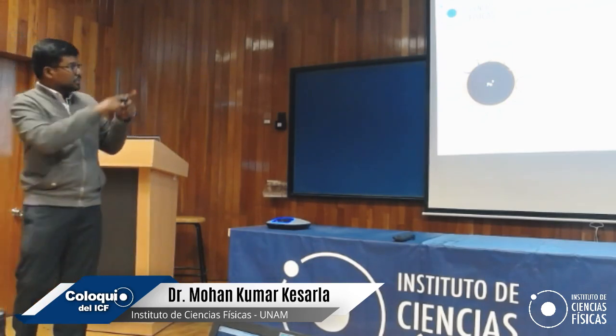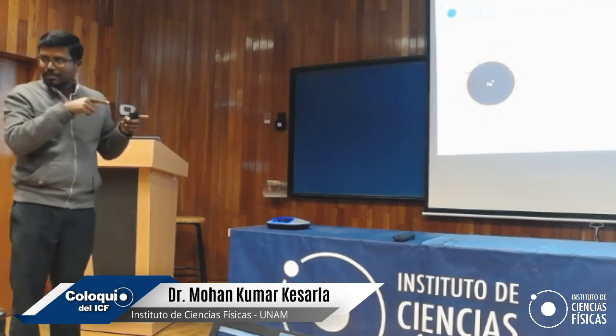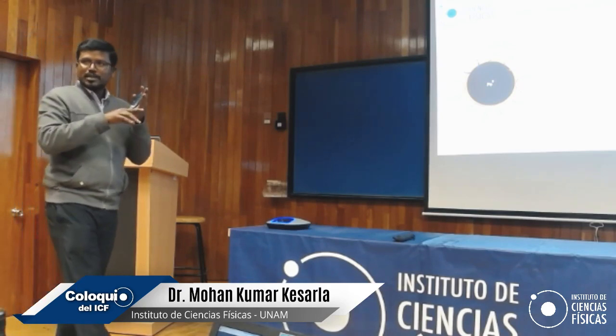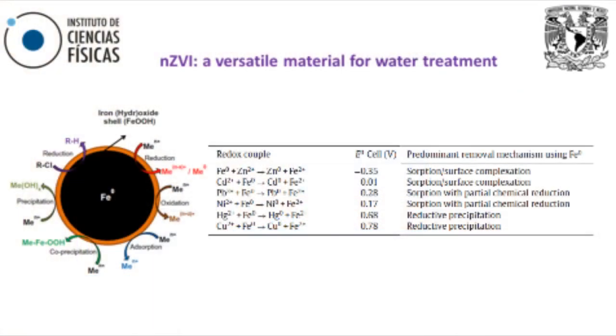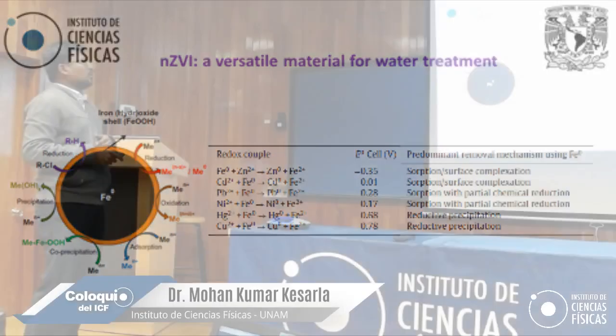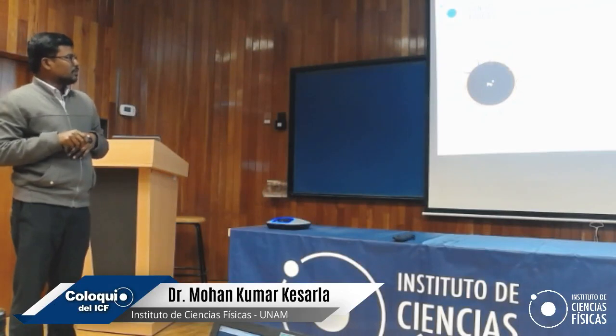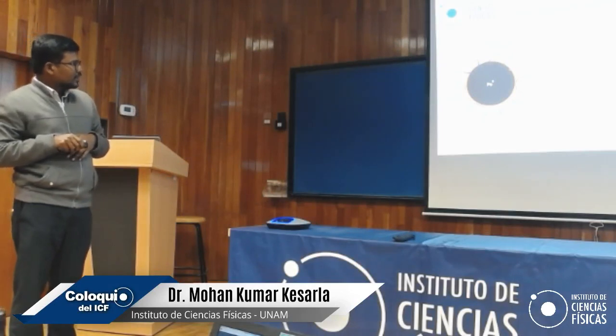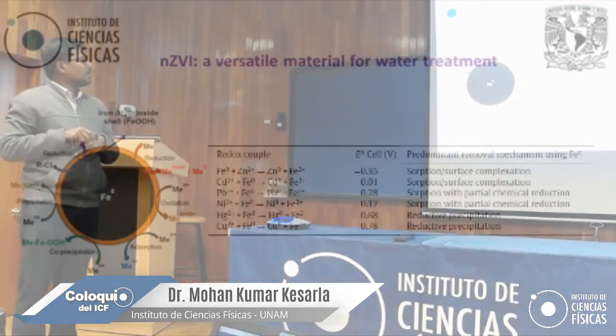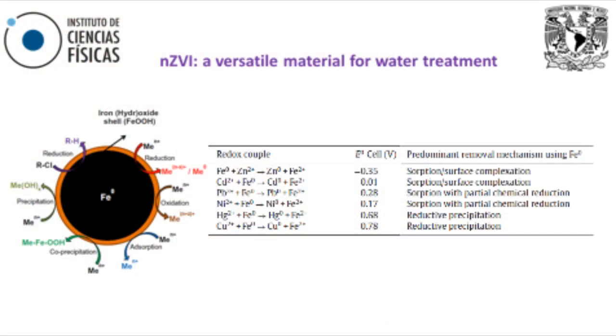But if you have a shell of iron hydroxide on it, reduction takes place, oxidation takes place, and adsorption also takes place. So this will be very good in increasing the efficiency of decontamination of water. You can see from this, starting from metal ions on the surface and onto the zero valent iron, different processes are occurring in decontaminating the water.